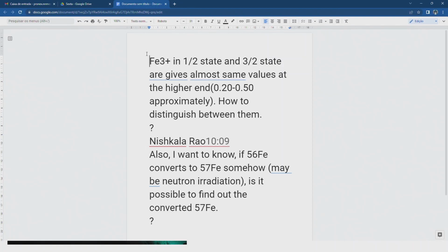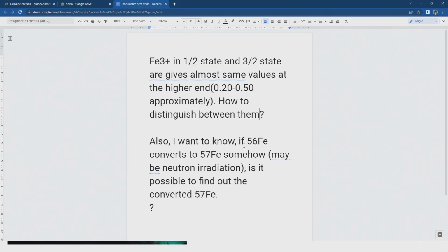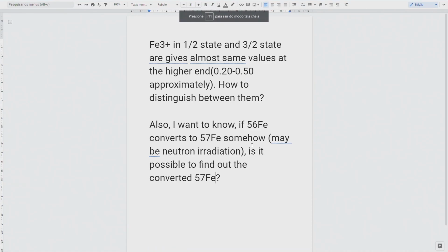So it's a good question about how to distinguish. It's not so easy. For example, there is one case, and I have worked on it, is how to distinguish when you have, for some minerals, pyrite in addition to other systems containing iron 3 plus. But pyrite, FeS2, is composed of iron 2 plus, but in low spin state. And of course, it's difficult to distinguish. So there is no direct method. So we have looked by comparing our Mossbauer data with some other data, not to conclude, but to estimate the maximum it could be or not. Because of course, the two doublets are strongly overlapped.